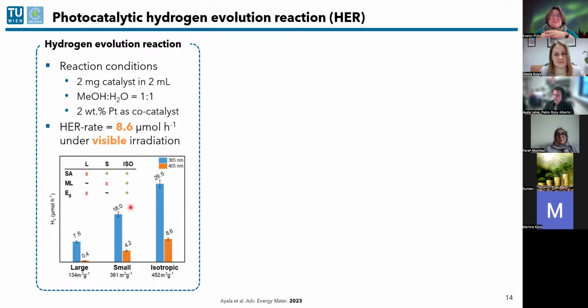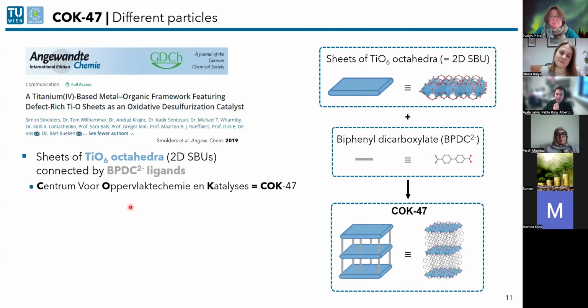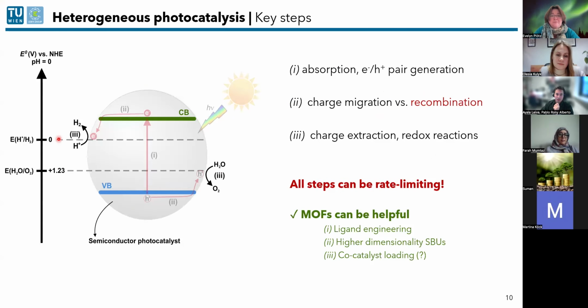So platinum apparently works, right? Yeah, platinum works very well because it's a noble metal and it's very good for adsorbing protons and then also desorbing hydrogen. So you want to have some affinity to protons, and then you also want to not have so much affinity that the hydrogen stays there, but it gets released. That's this step, right? So the surface reaction. If the hydrogen just sticks there, it's not good. And platinum just happens to have this optimal spot in the volcano curve as well.